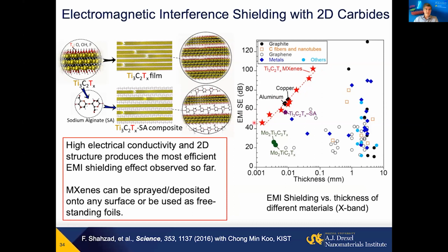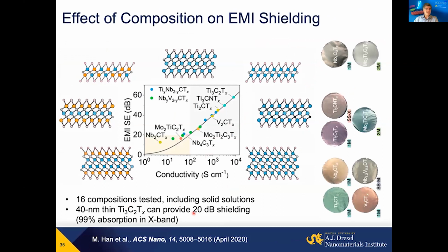Moreover, it's possible to achieve about 50 decibel. So basically 99.999% protection from electromagnetic waves with just a 1 to 2 micron film of MXene. Later, we showed that it's possible to get 20 decibel, which is sufficient for many applications, 99% of shielding, with just a 40 nanometer thin film of titanium carbide Ti3C2. And a variety of other MXenes can be used.